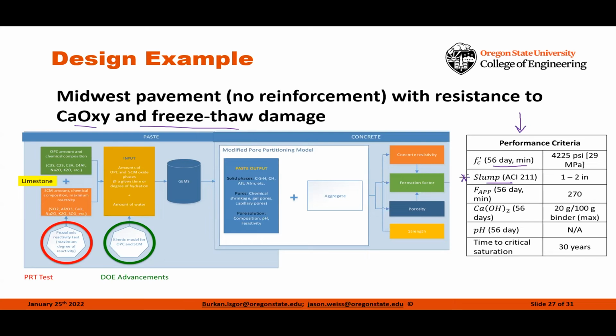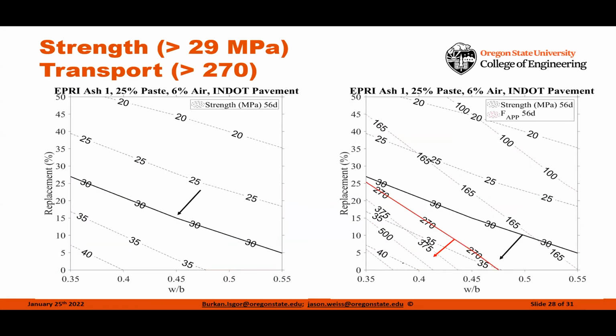This is one that we're not predicting right now in the thermodynamic modeling. We want to have a certain transport property, right? We want a certain time to corrosion, and we know what that's going to be if we know our formation factor. We need to have a certain calcium hydroxide content to make it resistant to our deicing salt damage. We may want to specify a pH to help us out with our ASR in this system, and we can have a freeze-thaw time to reach critical saturation. We can input all of these as the performance that we're trying to meet with our mixture, and we can then start to come up with predictions simply using the software that can help us look for what the right mixture composition is going to be.